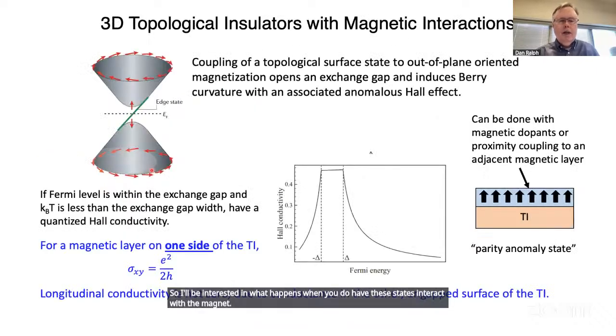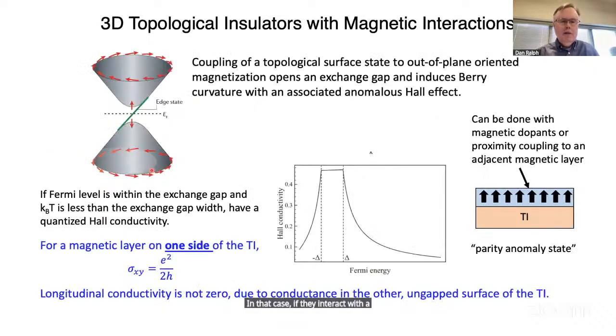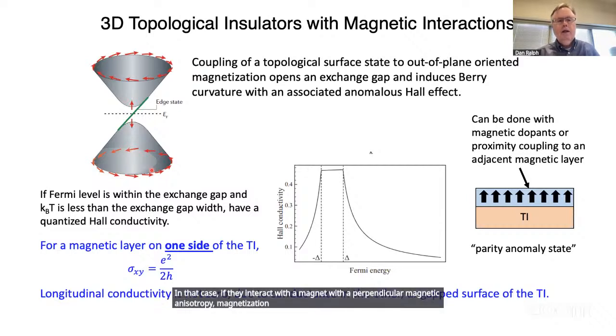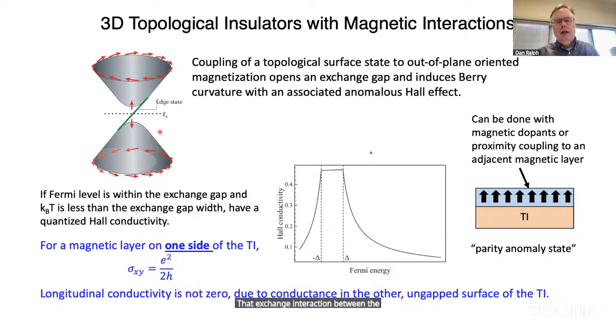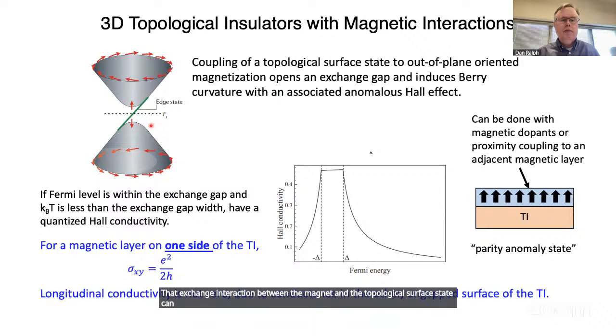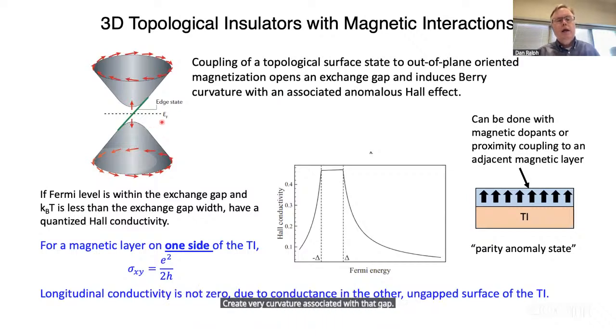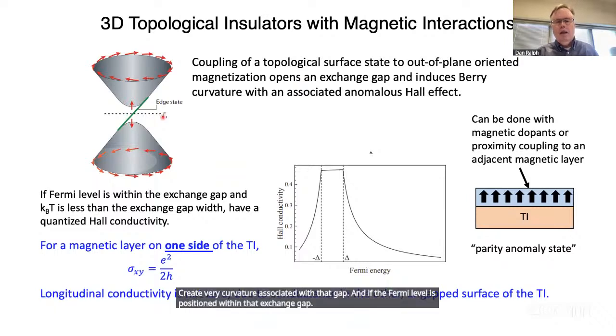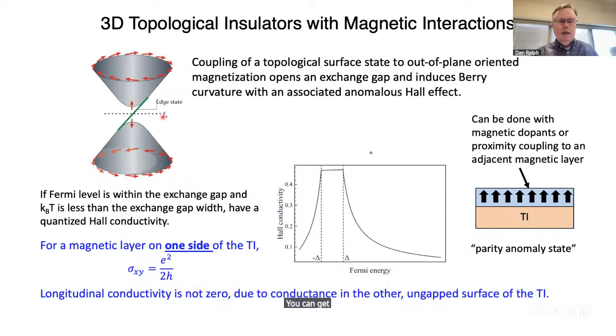In that case, if they interact with a magnet with a perpendicular magnetic anisotropy, magnetization pointing out of the sample plane, that exchange interaction between the magnet and the topological surface state can open up a gap in the topological surface state, creating Berry curvature associated with that gap. And if the Fermi level is positioned within that exchange gap, you can get an anomalous Hall effect, and it actually has a quantized value.